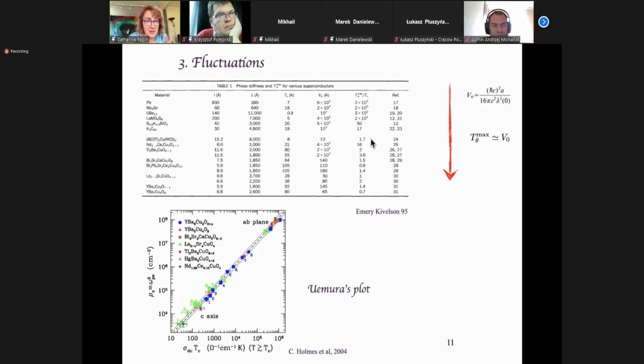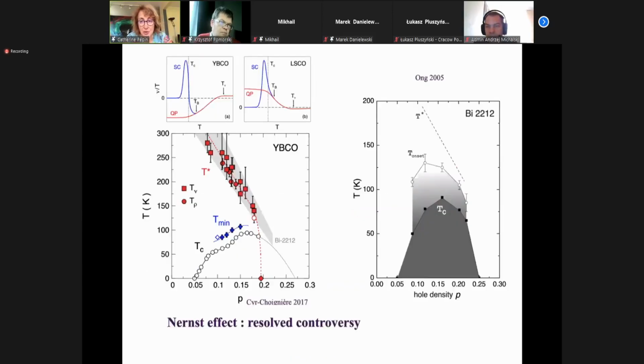What Emery and Kivelson did, they found a way by looking at the maximum temperature at which the vortices occur compared to TC. And then they were able, this way, for various superconductors, to give an idea of what is the phase rigidity of the superconductor. And you see that the phase rigidity for YBCO is maybe 10 to the power 5 less than for a superconductor like lead. So there is a huge difference with normal metal superconductors for phase rigidity. So, okay, fluctuations are there.